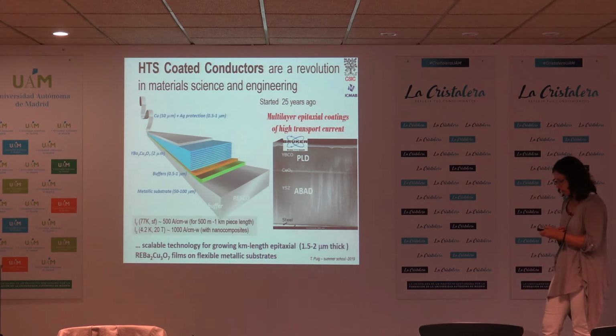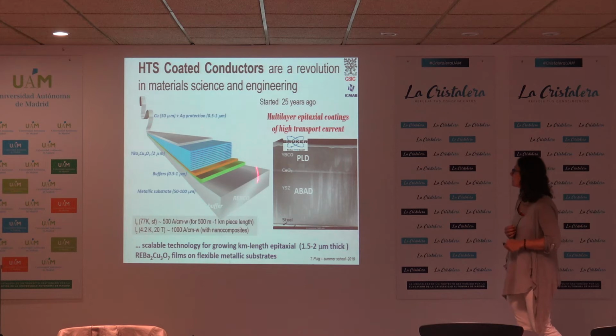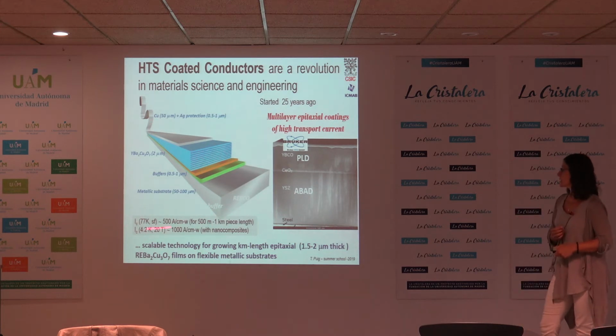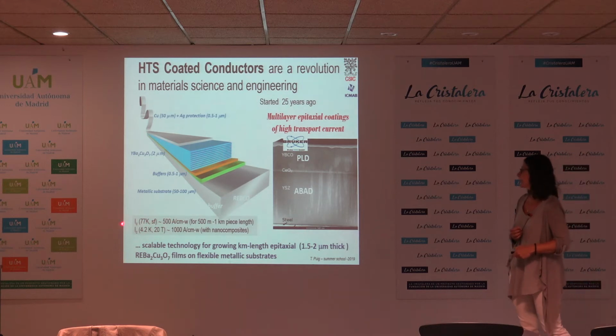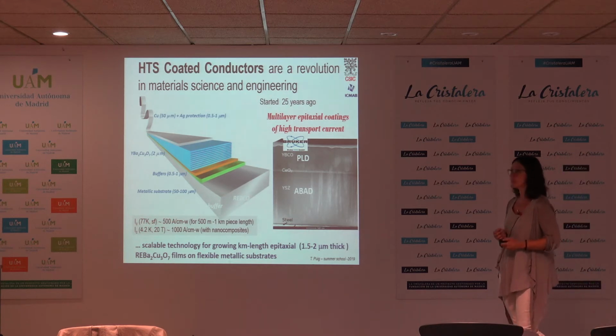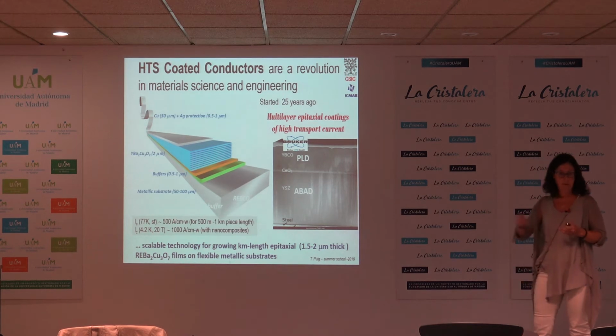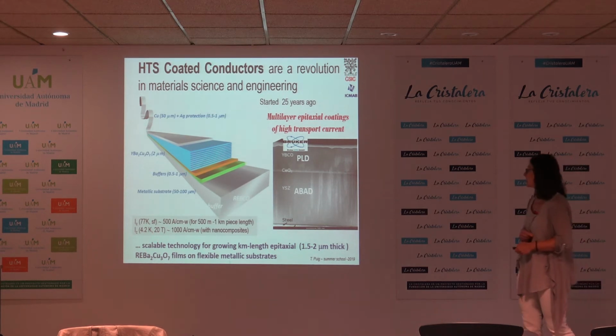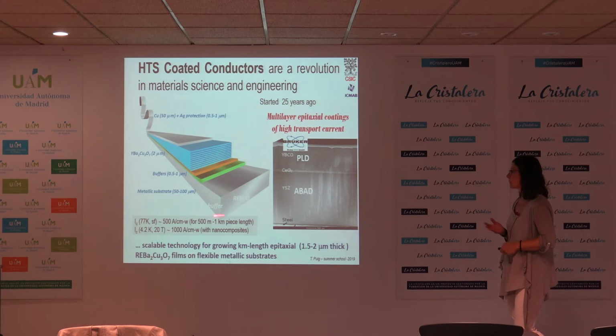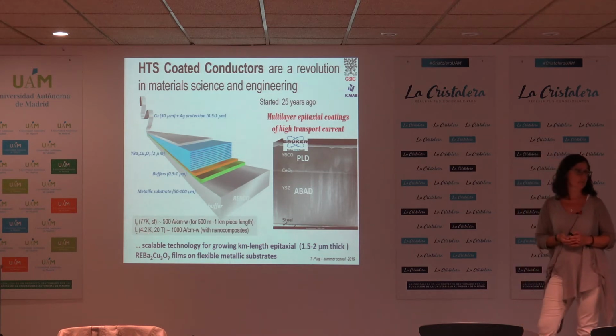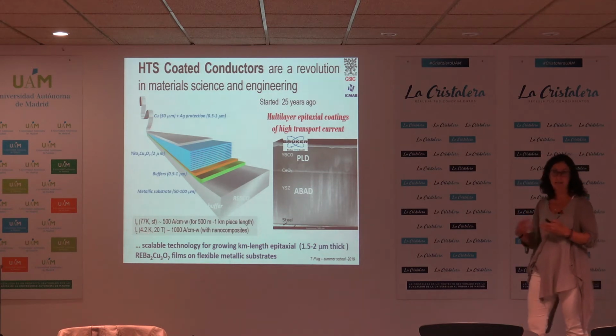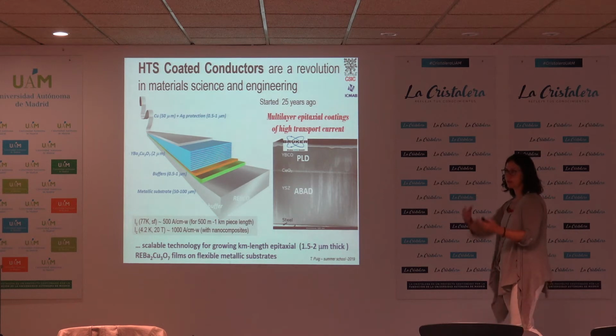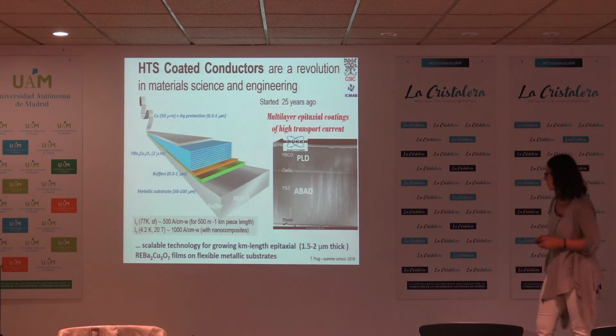And it has been now already 25 years working on being able to prepare these materials. And at this moment, we already can say that we have several companies able to produce 500 amps in 1 centimeter width tape at 77 Kelvin, in lengths of 500 meters, 1 kilometer. But if we go to 4.2 Kelvin and 20 Tesla, we can pass over 1,000 amps. So clearly this material at the end, 25 years later, could really demonstrate that it was a high current material.